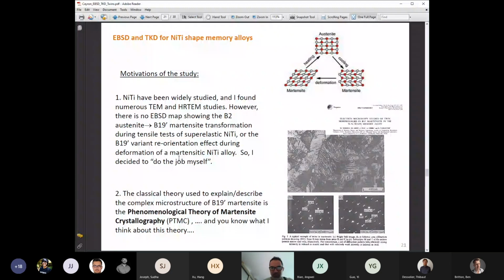And for decades and decades, what people used is TEM. They use TEM to show martensite, as in the image on the right. But by TEM, you just look at a small area. You cannot study a lot of grains, and the indexation is difficult. During a TEM session, you can index 10 grains. You have to tilt your samples. You have to find the good orientation. It's really hard work. So to make some statistics, it's really not good.